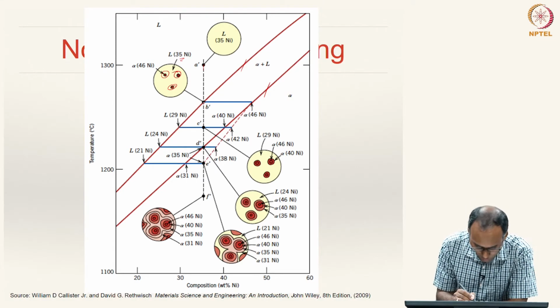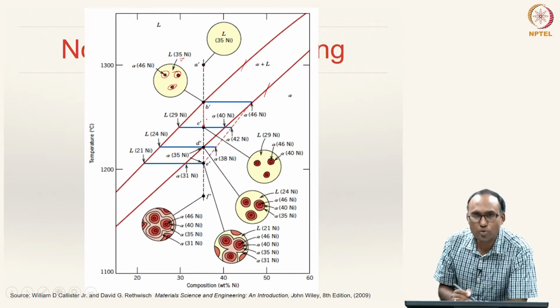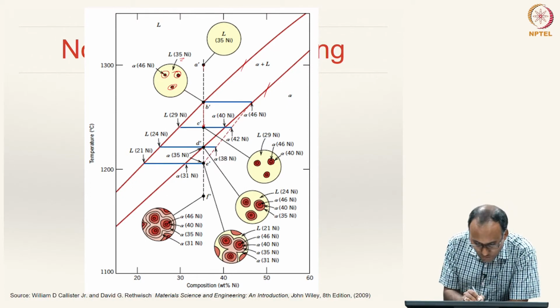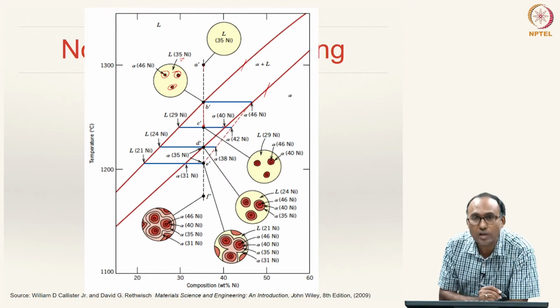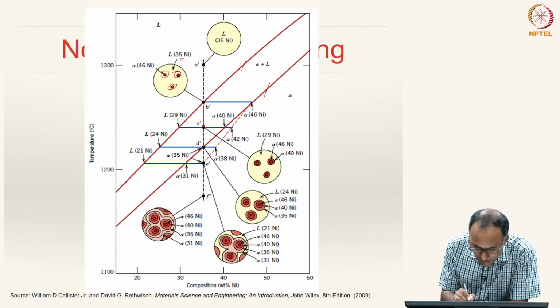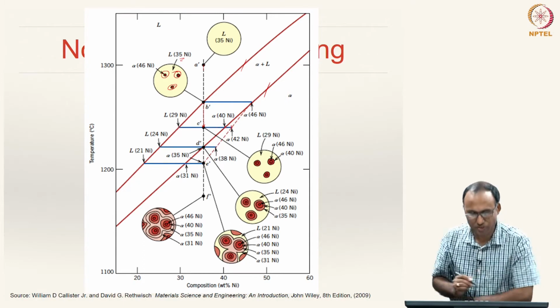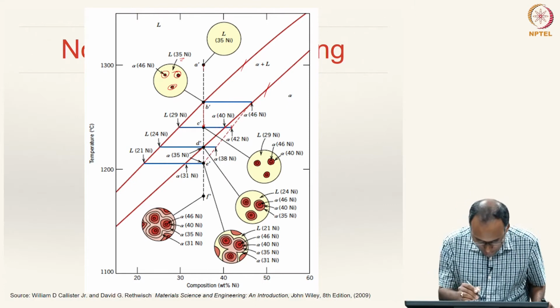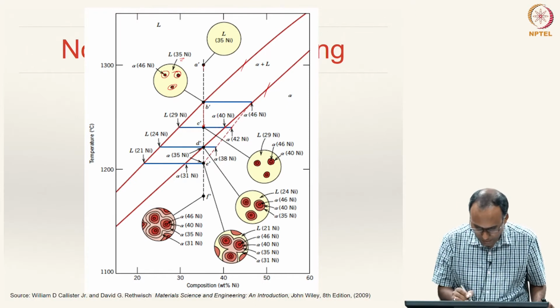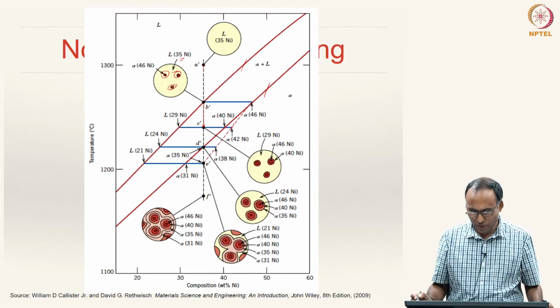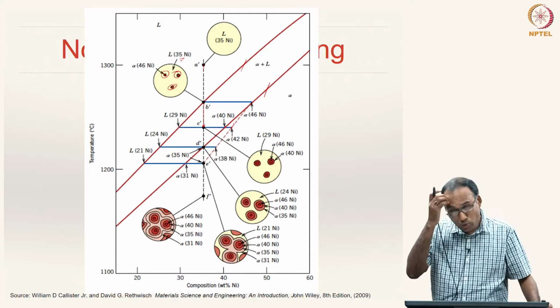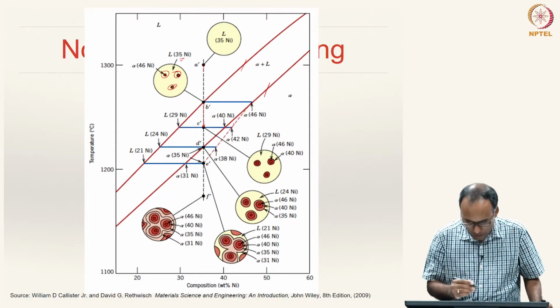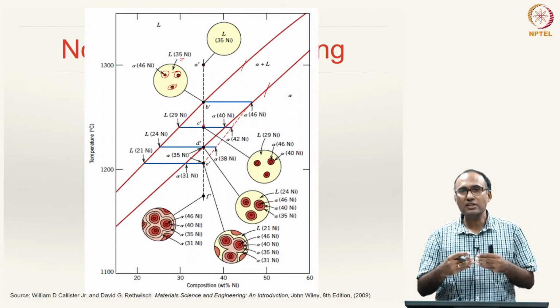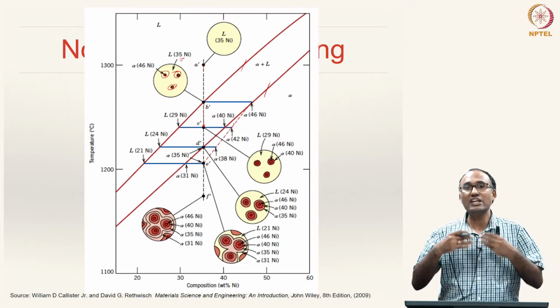Now, let us say we are cooling down to C prime, C dash. Then if you draw a tie line, if you had done the equilibrium cooling, it should have got 40% nickel, but because we have done it in a non-equilibrium fashion, the tie line hits the solidus line at 42% nickel. And please keep in mind that this is 46% nickel, and here you should have got 42% nickel, right, because you are cooling at a faster rate. But because you are cooling at a faster rate, the solid state diffusion does not have enough time.